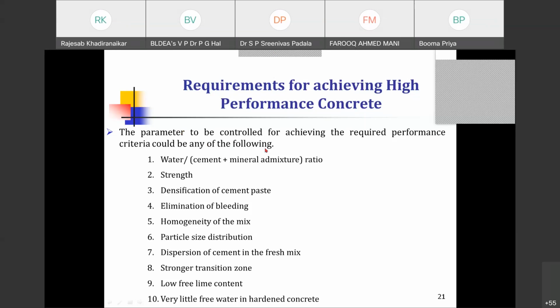And then you need to control the strength. You have to concentrate on strength. If the strength is more, naturally the durability characteristics will also be improved. Then the densification of cement paste, particularly the transition zone, where in conventional concrete you have a bigger transition zone and a lot of porosity. So densification of cement paste is being done. Then elimination of bleeding. Anyway, we are going in for reduced water content. Water binder ratio means reduced water content indirectly. So the bleeding is eliminated to a larger extent.